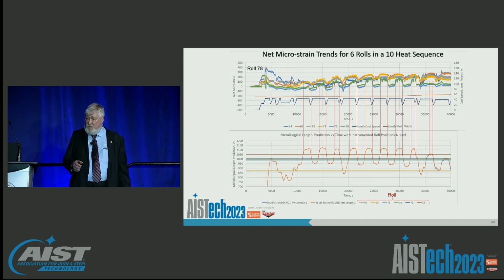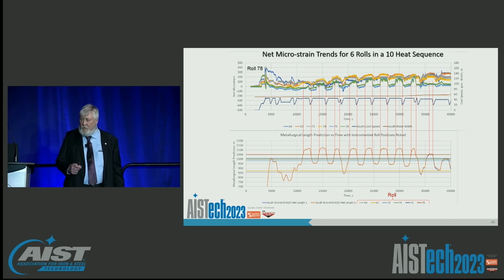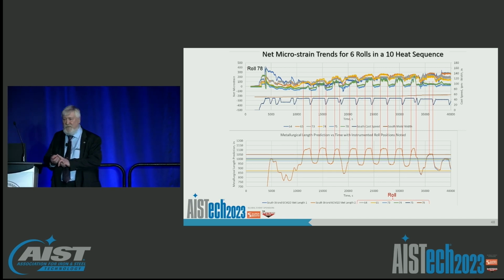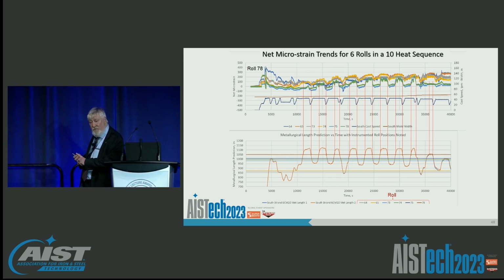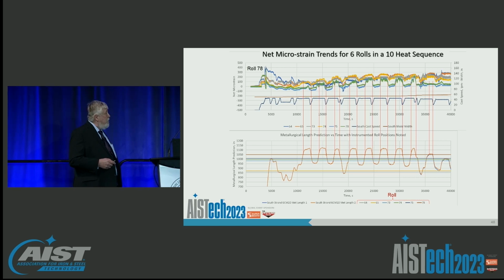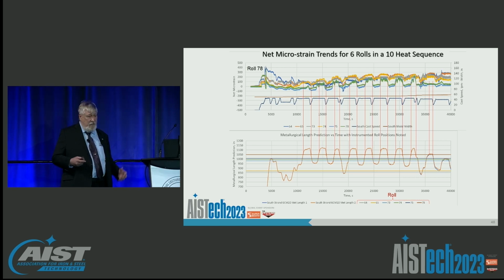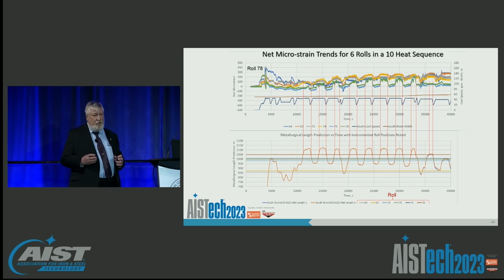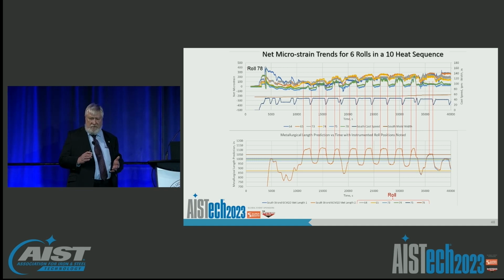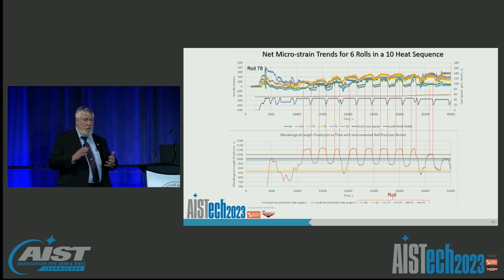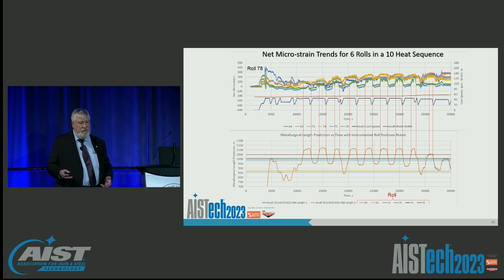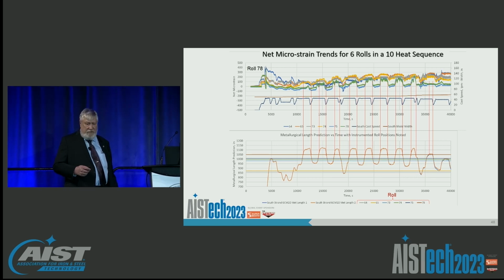In a couple of cases, we actually see operating conditions that cause a deviation from their model prediction, largely because of changes in mold heat removal that aren't accounted for in the model. And so these are going to be great tools if you're running a continuous caster and you need to know where your liquid core is, either for productivity or if you're doing soft reduction to improve center line. These are really great tools that can be used, and they're relatively easy to install.